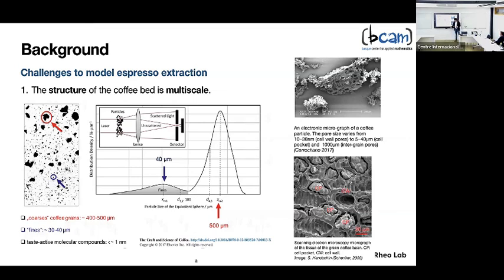Then, of course, we have the organic components, the material that we want to extract, the molecules of caffeine, trigonelline, and so on. It's not only this. If you look at these solid particles, the internal structure is not homogeneous, it's heterogeneous itself. In fact, coffee is a plant. So there is a level of porosity inside, represented by cell pockets, essentially cavities where the cells were originally contained, which have been destroyed during the roasting process.